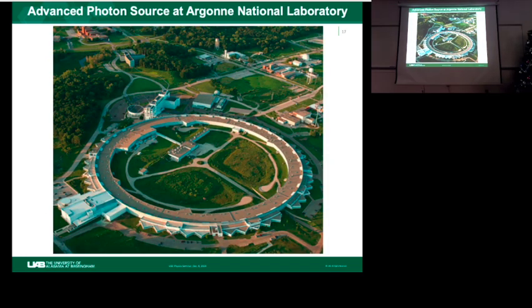Okay, so another technique we commonly use is synchrotron-based X-ray. The reason to use a synchrotron-based X-ray is that the diamond, although it's optically transparent, actually absorbs X-ray heavily in a certain energy window. For example, at several kiloelectron volts, after 2 millimeters of diamond, which is the typical thickness we use, almost nothing is left. The absorption is 99-point-something percent for that energy.